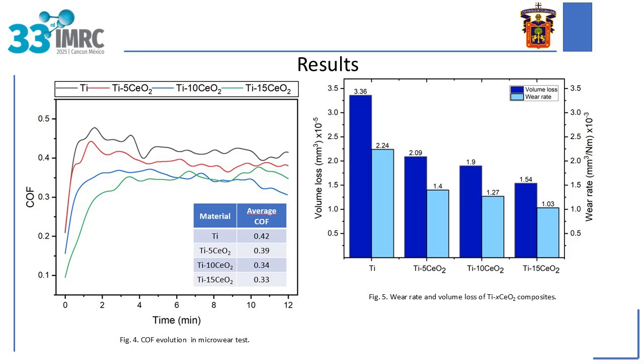The addition of ceria to the titanium matrix promoted a decrease in the friction coefficient, yielding the lowest values for the composites with 10 and 15% reinforcement. In the titanium 15 ceria composite, an increase of this parameter is observed starting at minute 9, likely due to the rise in ceria particles detached during contact, which acted as a third body and caused abrasive wear.